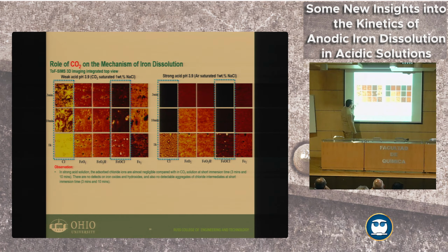So it seems that chlorides, when they adsorb, create some kind of an environment where, when they cover the surface, there are certain parts of the surface that they don't cover, and those are covered by an oxide or a hydroxide, etc. So you have a differentiation of where the chlorides are and where they're not. They're never completely occupying the surface, whereas in non-CO2 solutions, you have a more uniform coverage. So the direct answer, I would speculate that chlorides always lead to a non-uniform adsorption of other species, which eventually may lead to localized corrosion at these locations. Now, these are very small, nanometers, which may later on grow to become larger. So there's something about the non-uniform adsorption in the presence of chlorides, in this case CO2, which may lead to localized corrosion. But do we have a better understanding from this study?